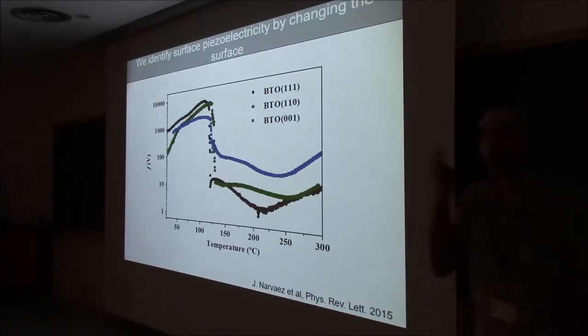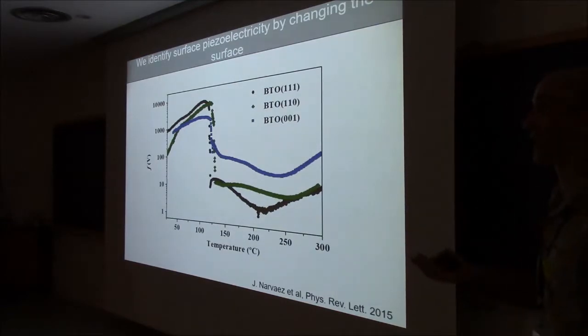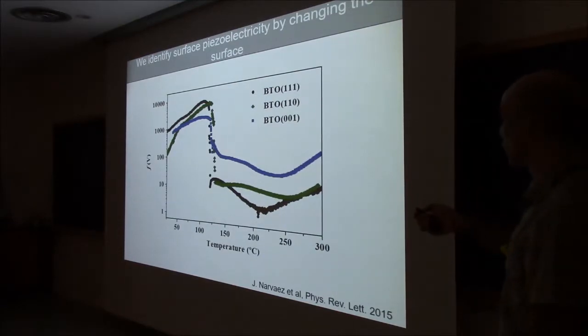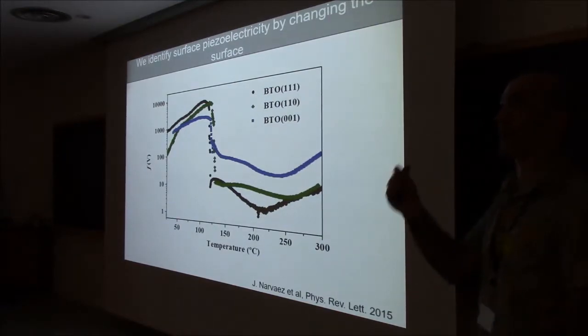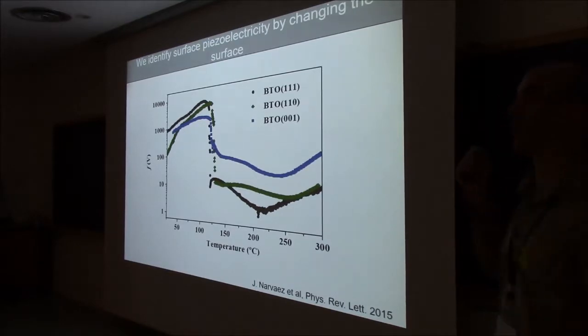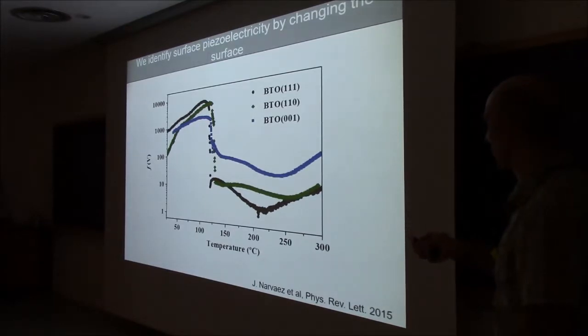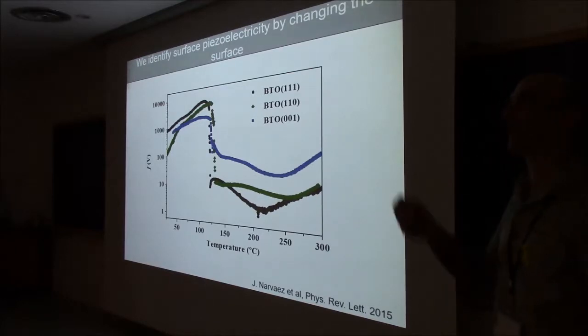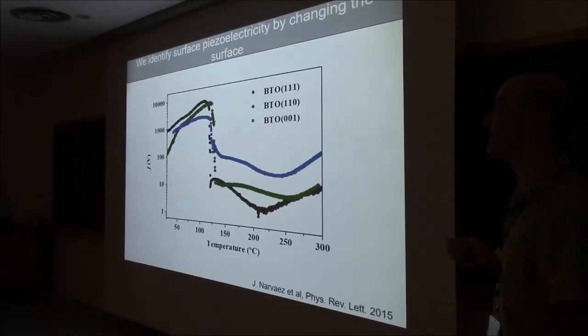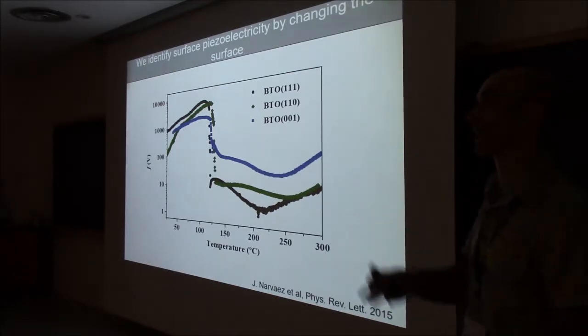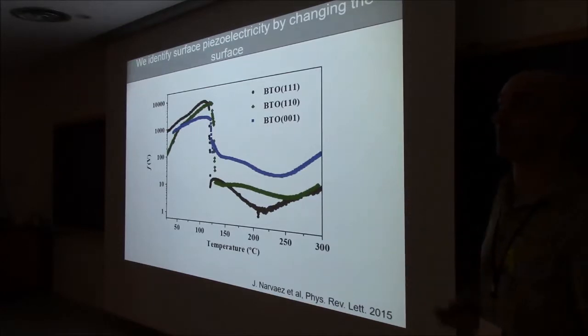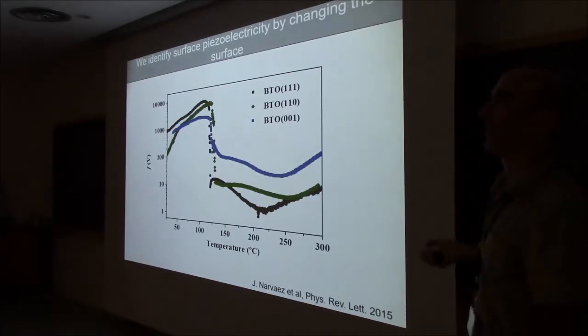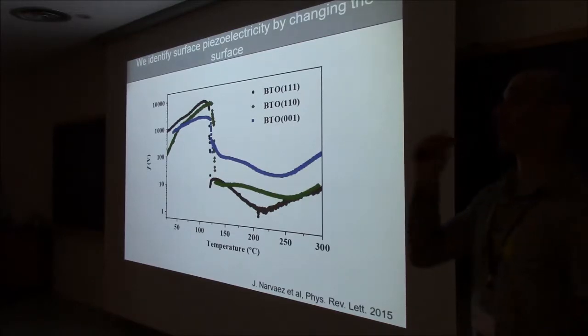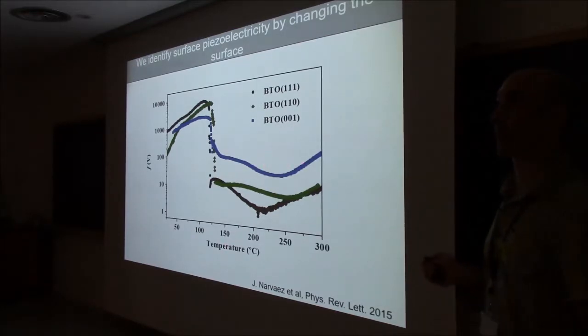Okay? I mean, it's not a big effect at the macro scale. The thing is, once you know the size of the coefficient, then you can extrapolate: you multiply the flexo voltage coefficient times the strain gradient, and you know what this can do for you at the nanoscale. And this is where things get really exciting. So we quantify the coefficient at the macro scale, but we measure the consequences of it at the nanoscale.